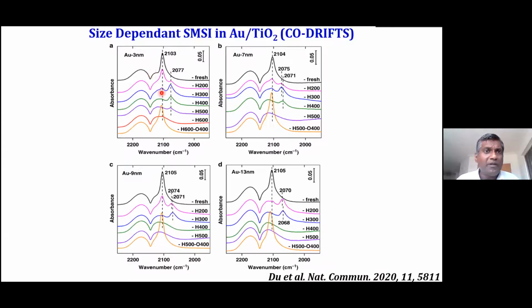They reported, as you can see, for 3 nanometer gold, even after reducing the catalyst at 400, they could still see some level of CO adsorption. Whereas for 13 nanometer gold particles, at 400 it is completely gone. I mean, there is no adsorption of CO at this stage. So they more or less observed what we observed for the platinum on titania situation.